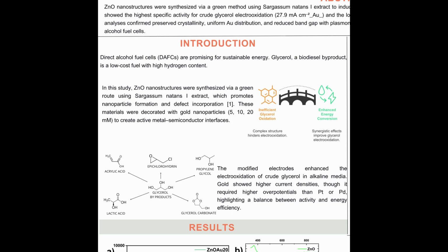Direct alcohol fuel cells are promising energy conversion devices because of their high energy density, mild operating conditions, and compatibility with renewable low-cost fuels. Among these, crude glycerol is particularly attractive as it is an abundant and inexpensive byproduct of biodiesel production, has a high hydrogen content, low toxicity, and can be converted into value-added chemicals through electrooxidation. The main challenges are its complex molecular structure, which slows oxidation kinetics, and the presence of impurities that can poison the catalyst surface. These issues require highly active and stable anode catalysts.